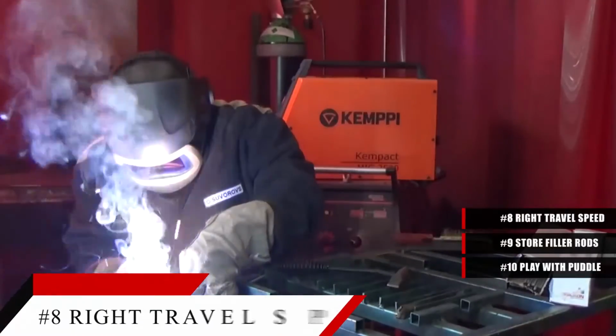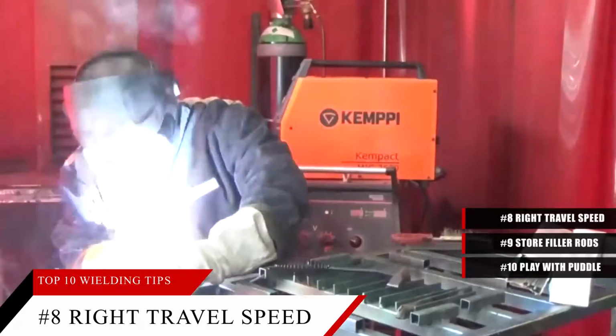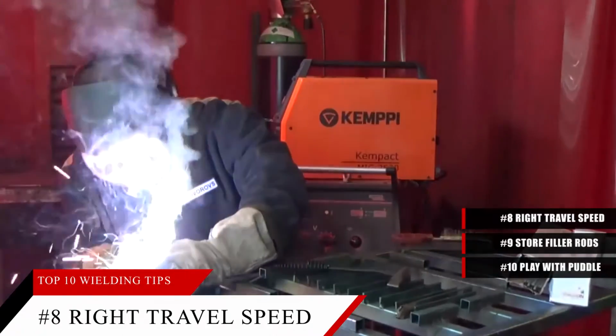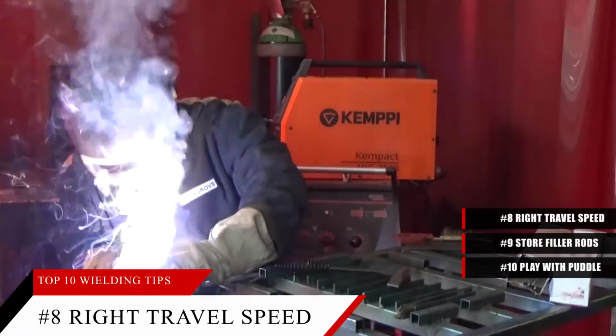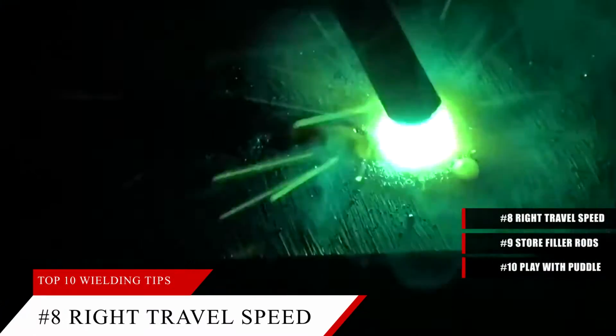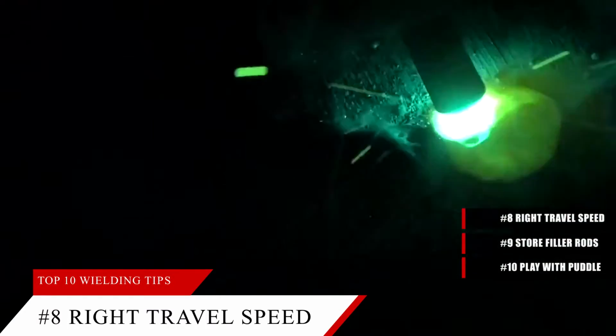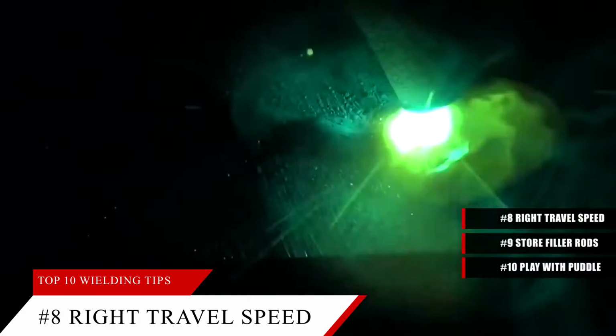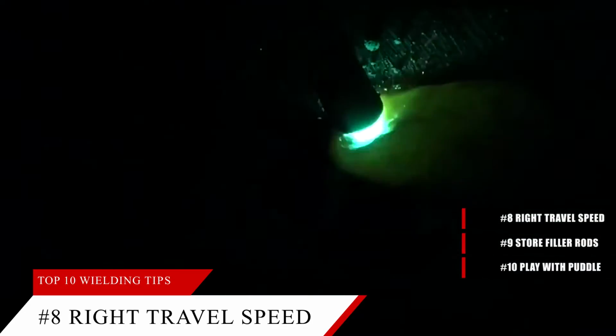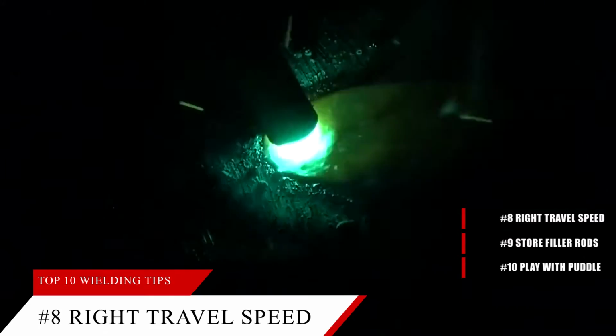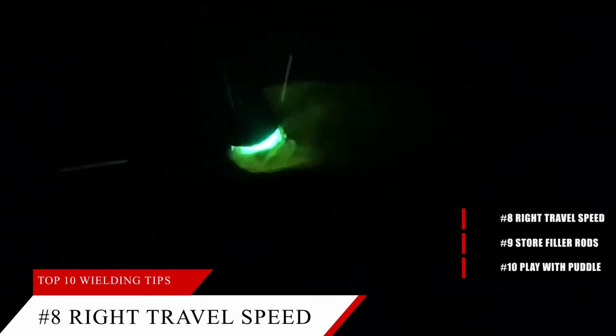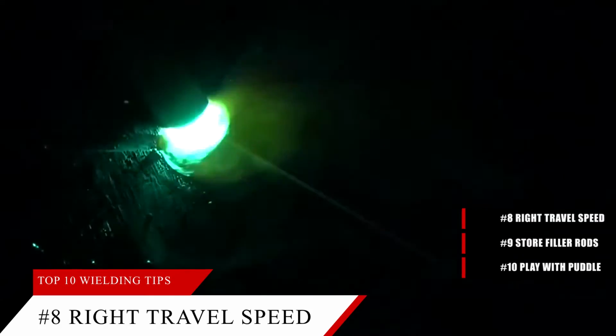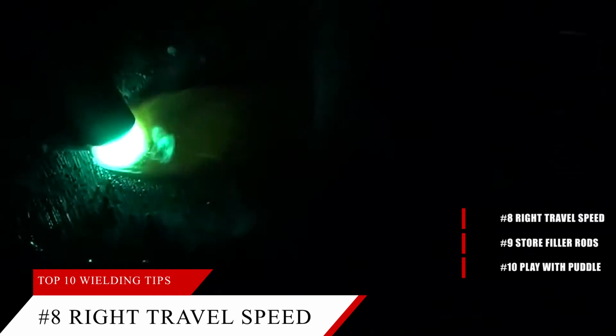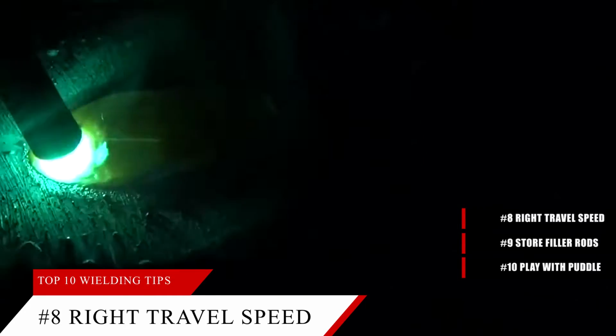Find the right travel speed. The correct travel speed will keep the arc in the leading third of the puddle. Traveling too fast or too slow has different consequences. Welding too slowly will deposit too much material into the puddle, creating a convex weld bead that often lacks proper penetration and appears to be sitting on the surface of the base metal. It also tends to focus the heat into the puddle instead of the base metal, further weakening the weld.